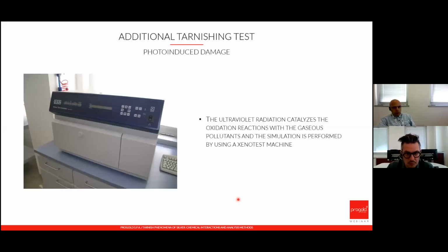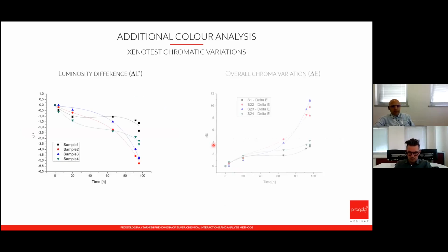Additionally, in order to extend the study toward more real and complex conditions, the effect of sunlight on sterlings was simulated by ultraviolet irradiation and performed in a xenotest machine set with a power of 1.4 kilowatt at 60 Celsius for 4 days in natural atmosphere. With a quite different result, because sterling silver this time showed the lowest color difference, followed by commercial alloys. Conversely, the pure silver and the silver-plated sterling showed the highest color damage under ultraviolet beams.